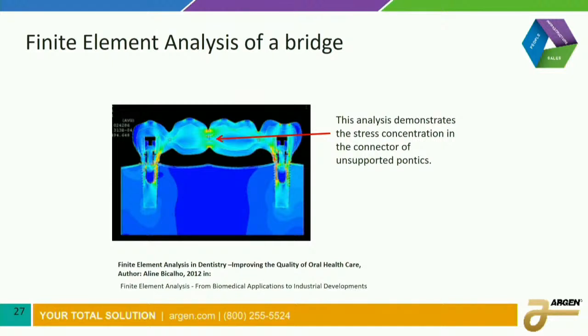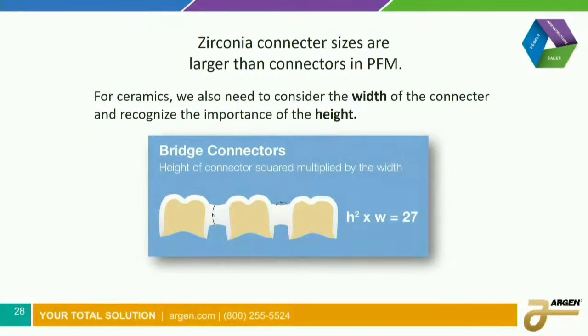So that looks okay. But generally, we don't get fractures on bridges like this. So maybe the fact that it happens to be a 5Y is sort of incidental to the actual reasons. Now, our friends at Glidewell gave us this nice formula for connectors, and most people have been following it. The width of the connector matters, but height is the most important factor. They demonstrated the height was most important by multiplying it by itself. So the height of the connector is the most important factor for zirconia. Just keep that in mind.